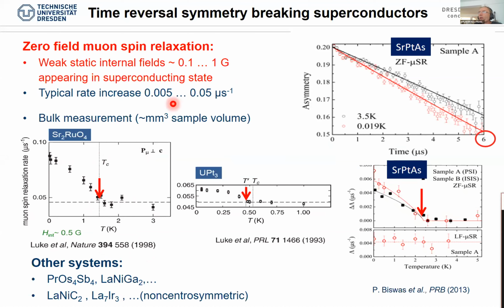This is also at the border of what one can measure with muons in terms of resolution, because we have to measure time-dependent spectra. And here on the right side, you see some other spectra which we measured some years ago on an even weaker case of time reversal symmetry breaking, strontium platinum arsenide. But you clearly see that above the superconducting transition, there is some sort of relaxation of the muon signal as a function of time. But below that transition, there is an increase, and we can measure these kind of signals.